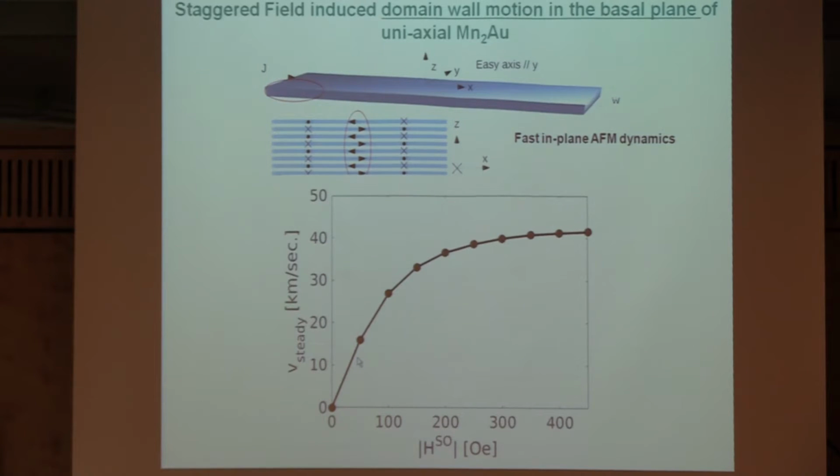What Alan also pointed out is that in an antiferromagnetic system, the Walker breakdown, the stability, is not such an issue. So with things like Walker breakdown, where the domain wall structure becomes unstable because you overcome a principal energy threshold, which is defined by the anisotropy of your system, typically the demagnetization field in the system.